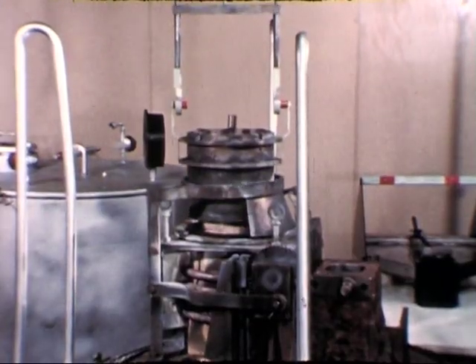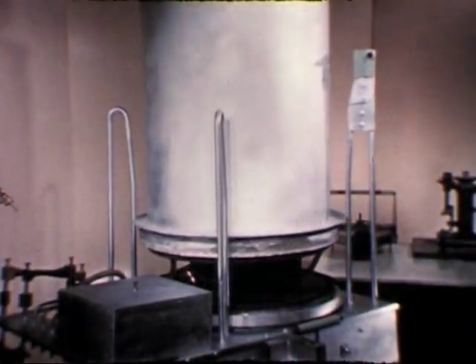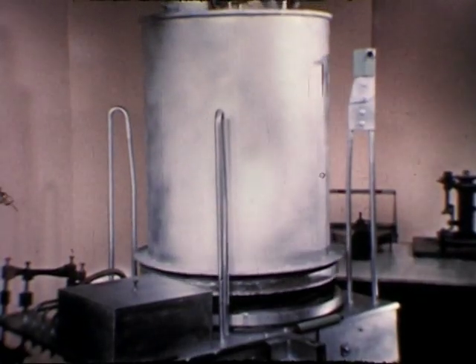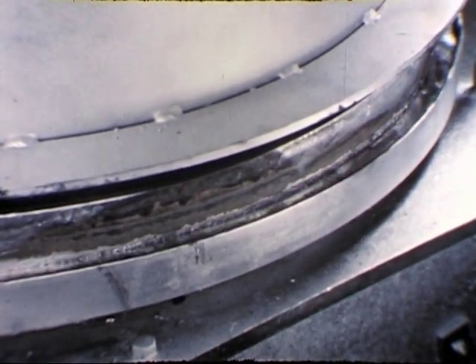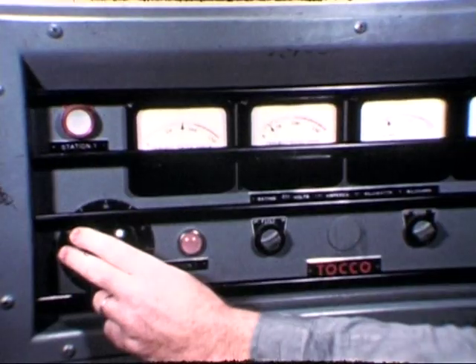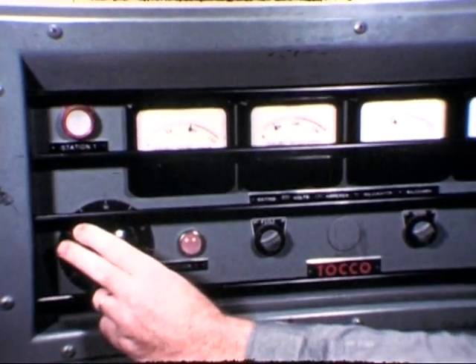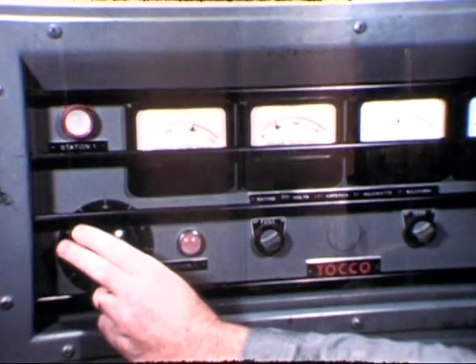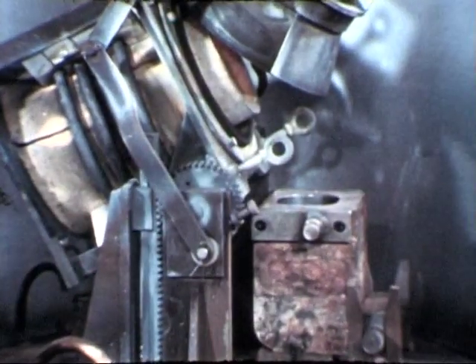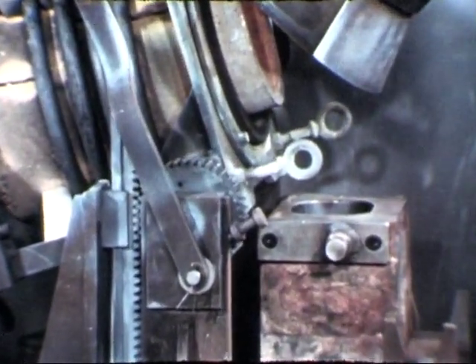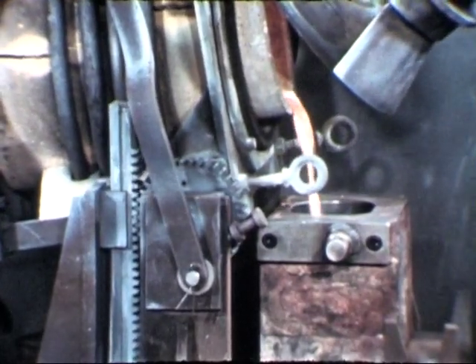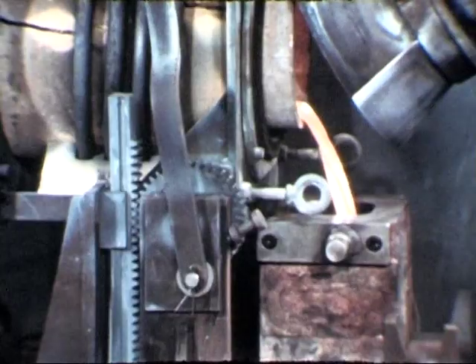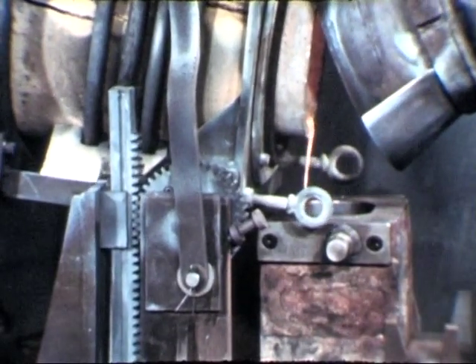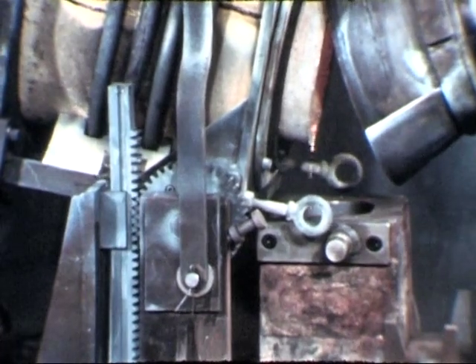The furnace is reassembled. The bell jar confines the gaseous fission products and is sealed to the furnace base by a molten metal freeze seal. High-frequency induction is used to obtain the melting temperature of 1,300 degrees centigrade. After a 3-hour liquation period, the melt is tilt-poured into a mold. The active metal fission products, which have reacted with the oxide crucible, remain behind as a slag. The more noble fission elements remain with the fuel alloy.